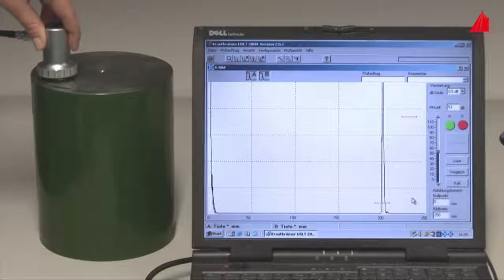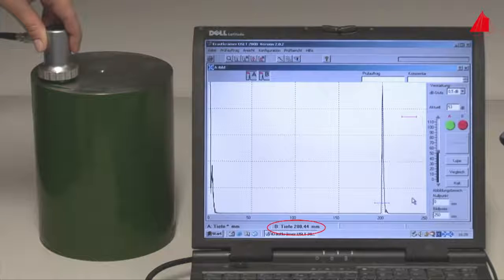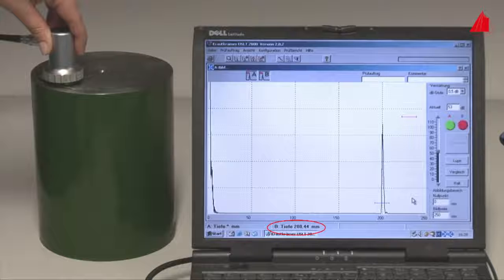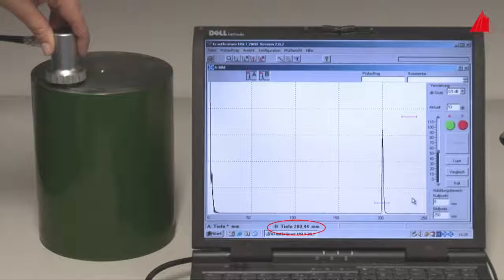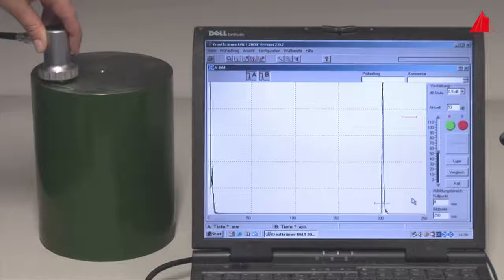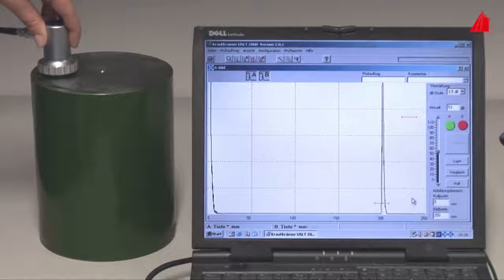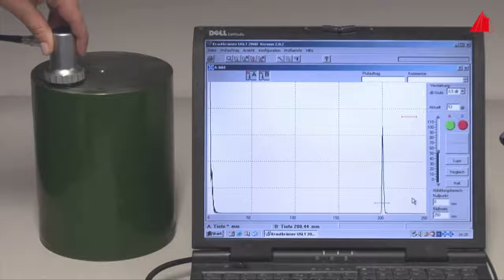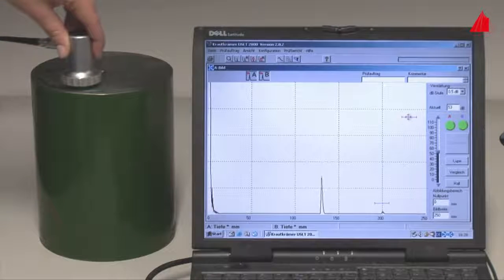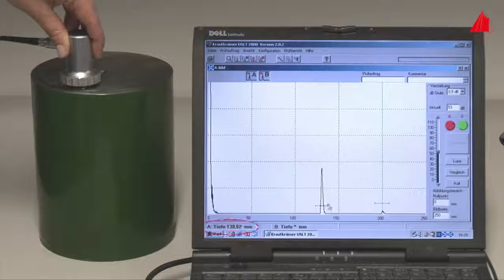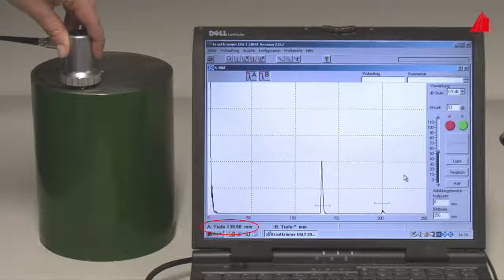At the lower left-hand corner of the monitor, the cylinder backwall lies in a depth of about 200 millimeters below the probe, so the cylinder has a height of 200 millimeters. And here we go: the material tester scans the upper front end of the cylinder with a probe and observes the monitor. A defect echo appears on the monitor. This defect is located in a depth of 130 millimeters below the surface.